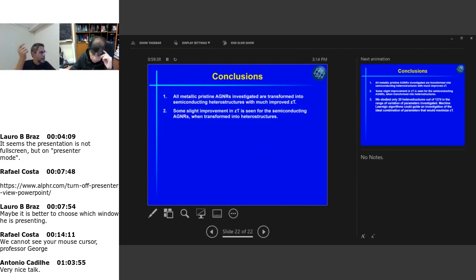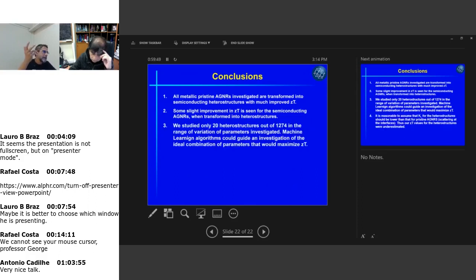There were slight improvements in ZT seen for some of the heterostructures that we studied. And there is a point that I didn't mention, and I'm mentioning now. We studied only 20 heterostructures out of 1,274 in the range of variational parameters investigated. You notice that I only showed the results for odd capital N, but we could have done the calculations for even also.